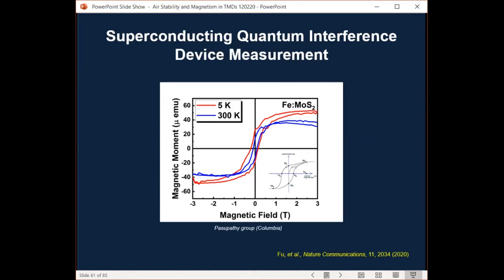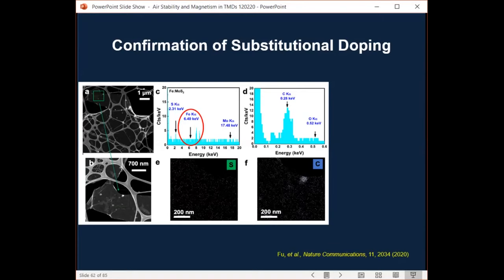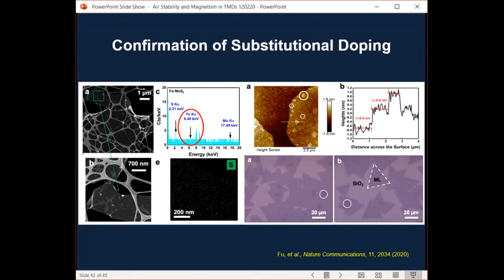So here, the iron doped molybdenum disulfide monolayers exhibit a pronounced hysteresis loop at both cryogenic and room temperatures. And here, the magnitude of the hysteresis loop decreases with increasing temperature. So here, 5K is red and 300K is the blue here, but the Curie temperature has not been reached at 300K. I think it's possible that the Curie temperature of this material is much higher than the room temperature, although we have no way to prove it. One concern regarding this doping process was about iron residues that might affect the magneto-optical measurements, but we measure everything after cleaning and annealing. So there shouldn't be any residue. But nevertheless, we have performed this series of control experiments per request by reviewers. So, low magnification STEM images here along with the EDS spectra confirm that the surface of iron doped sample is free of iron oxide sample. If there is any iron oxide samples on top, then you will see from the EDS. But again, we don't see the EDS is not sensitive enough to pick up the signal from substitutional atoms, but we really don't see anything. Here, the signature from the carbon is from the PMMA residue left during the transfer process to the TEM grid. The AFM images and optical images also further confirm that the surface of the sample is free from any potential residues after annealing and cleaning.